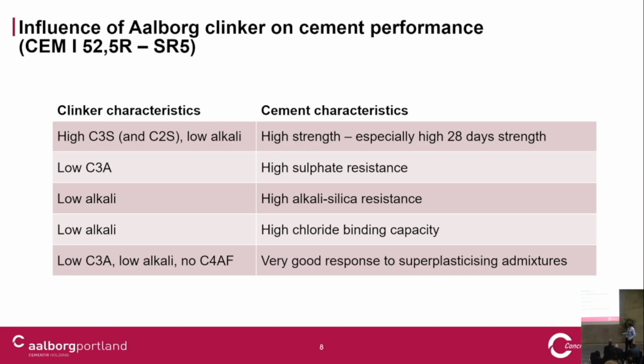Low C3A, low alkali, no C4AF - that means this clinker in cement gives us a cement which has a very good affinity, or very good compatibility, with superplasticizing admixtures.